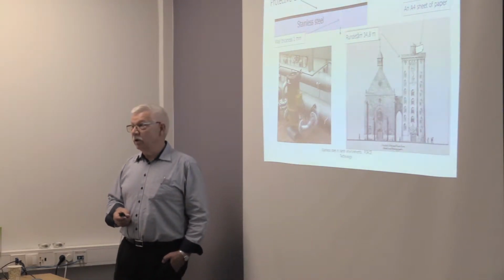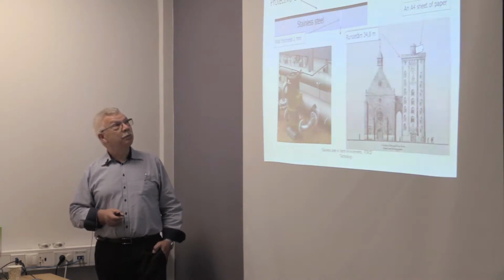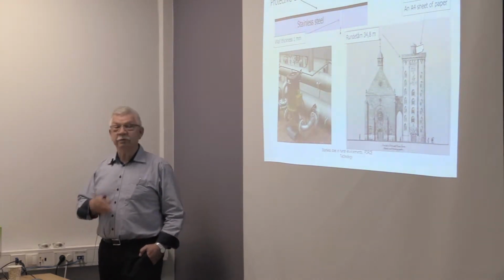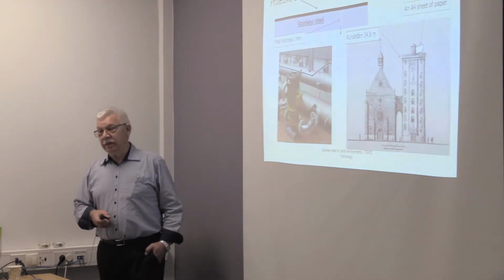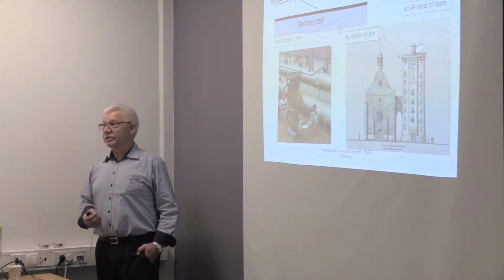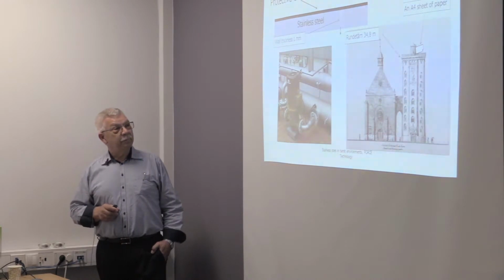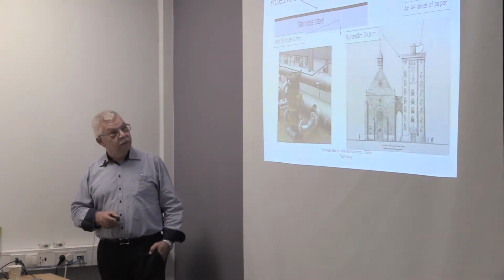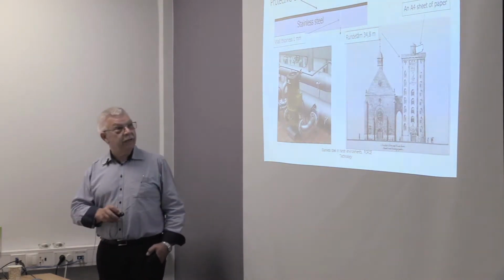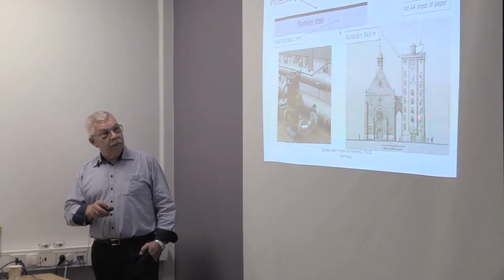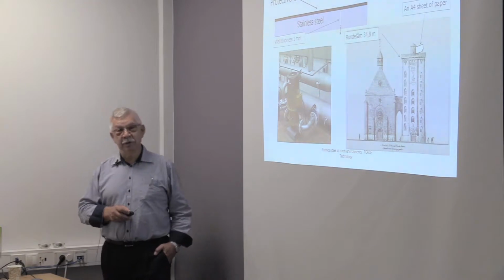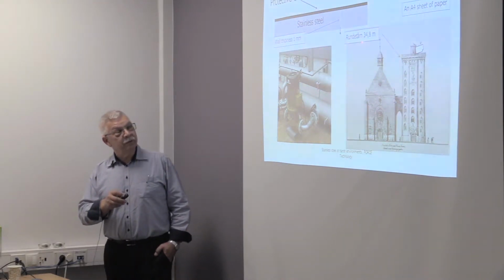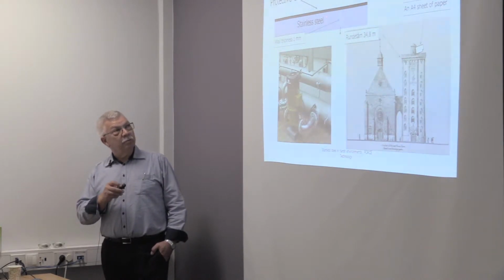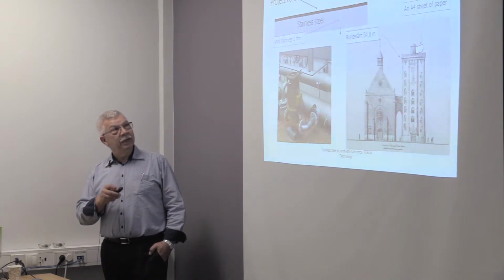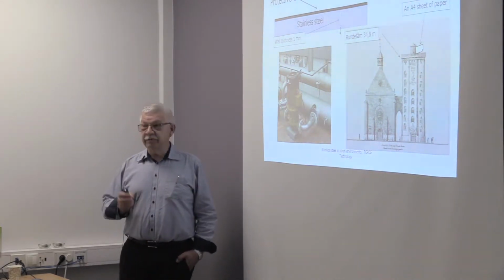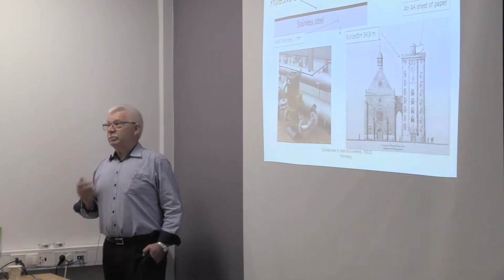The passivity of stainless steel is, as I said, in the chromium oxide layer on the surface, and the thickness of that is only 20 to 50 angstrom. I don't know how you feel about that, but it's hard for me to imagine how thin that is. The model that we usually use to describe that is to go into Copenhagen, where we have a church tower called Rundetårn, where we can go up, and if we bring a sheet of paper and place it on the top, then the approximately 35 meters of tower would be equal to 1 millimeter of stainless steel, and the paper would be equal to the passivity layer. So as you can see, it's very thin, and you will damage it at some point.